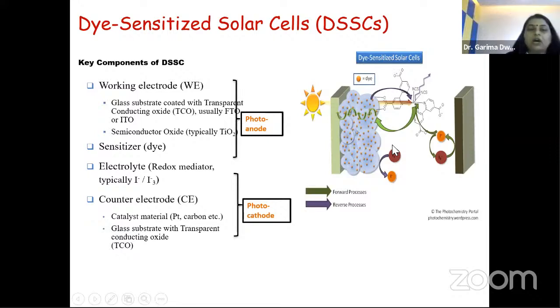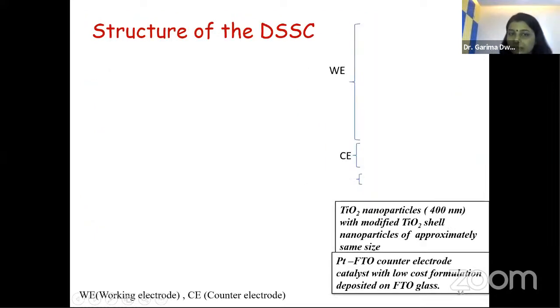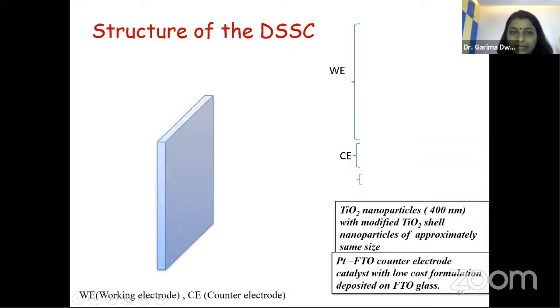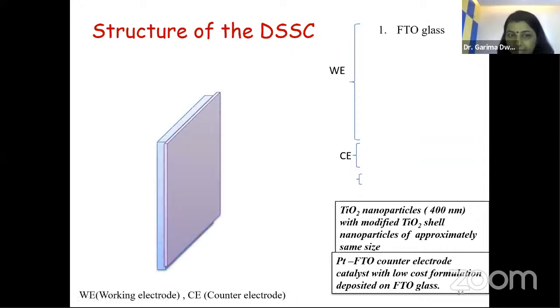Now how will the working of this third generation solar cell, that is the DSSC, happen? This is conducting glass, normal glass on which there is a conducting coating, that is FTO, fluorine doped tin oxide. Commercially, two types of conducting glass are available. Either we can use FTO or ITO, but we cannot use ITO in our DSSC because we have to sinter it. Stability will come as an issue, so we preferably use FTO in our case.